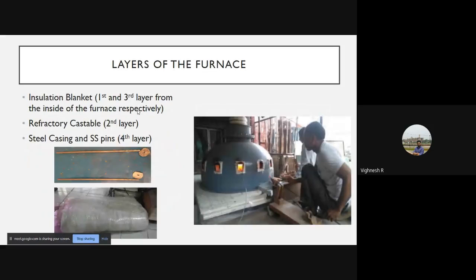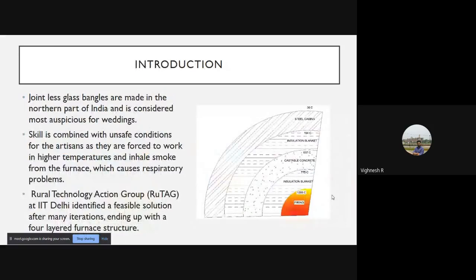Insulation blanket was the first and the third layer. The refractory castable concrete was considered to be the second layer. It's actually concrete. The fourth layer was steel casing, which housed the whole apparatus. If you go back and see this photograph, the firing will have a temperature of about 1300 degrees Celsius, and the insulation blanket was fixed as the first and the third layer. The castable concrete was the second, and the fourth one is the steel casing. And you see the temperatures which we wanted to have.